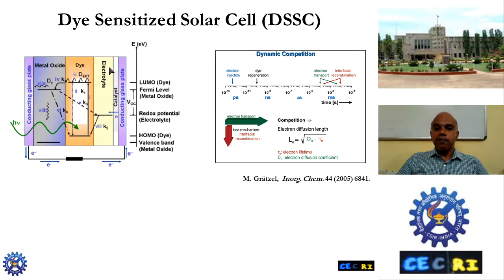So the time scale at which this process happens: the electron injection happens in picoseconds, and the dye regeneration happens in nanoseconds, and some of the recombination processes happen in milliseconds. So these recombination processes should be minimized. Of course, you can have certain blocking layers through which you can minimize the penetration of electrolyte or this back electron transfer from the conduction band of titanium dioxide to the electrolyte, or this blocking layer can also enhance the fast transfer of the electron. If you have a thin layer of such oxides, the fast electron transfer can happen to the external circuit.